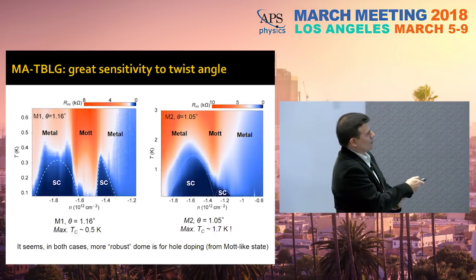Let me show you the data for the 1.05-degree sample. Here, the Mott insulator state is weaker, such that we can actually reach a metal to insulator to superconductor transition. You have the electron dome, which is much smaller.